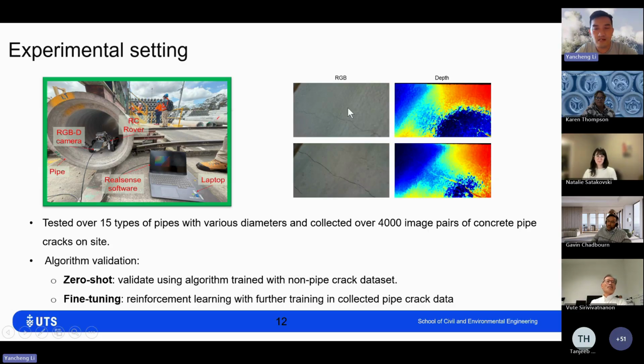Here we have an example of RGB and depth images. You can see the RGB image here with a very fine, thin crack, sometimes nearly invisible. The depth image looks messier in a way, because it is more like a color map. So we have to analyze those two inputs to get the features of the crack and locate it among the vast number of pixels of other concrete background, and get the features of the crack because it is very thin.